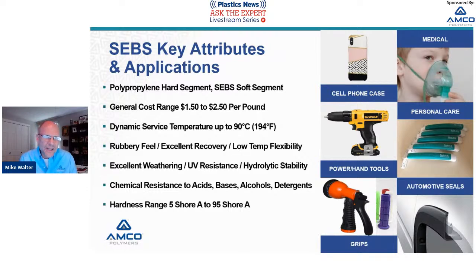So they don't make really good high heat materials, but alternatively, they're used for more room temperature and low temperature applications. They provide a really cool rubbery feel, excellent recovery, and outstanding low temperature flexibility. They also bring excellent weathering and UV resistance and hydrolytic stability, or resistance to moisture. As far as chemical resistance goes, they're resistant to most mild acids, bases, alcohols, and detergents. So they lend themselves to a lot of household item type applications. They have a very generous hardness range of 5 Shore A to 95 Shore A, so you can get really soft with